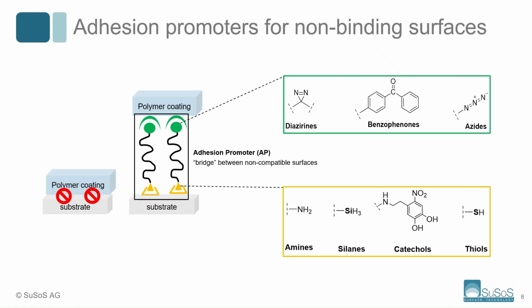And as you can see, depending on the material of the substrate, and also the coating on top, polymer, nanocellulose, etc., we use different groups. So for substrate binding, we have amines, silanes, catechols, thiols, whereas for the top, so the add layer, polymer or nanocellulose coating, we use various diazirines, benzophenones, and azides. And in our case at SuSoS, we use azide as the bonding group to the add layers.